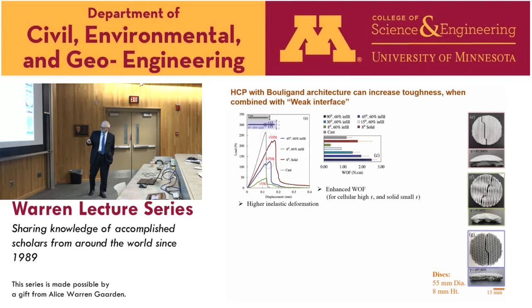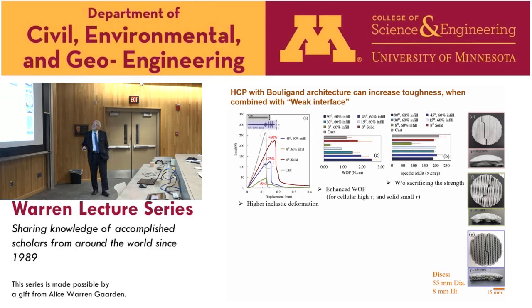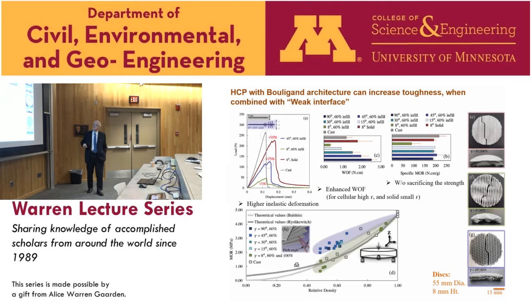If you look at some of the mechanical characteristics, for example, work of failure, or even the ductility, if you look at the area under the curves, you can see that orientation of those filaments matters. And you can see that if we have, for example, this structure that has 40% less material, it actually behaves almost like the solid materials that we cast. And the other thing, this is a look at the modulus of rupture, and you can see that we didn't sacrifice the strength very much by not infilling it completely, just by keeping the orientation that was different.